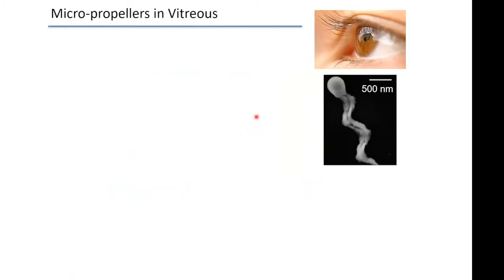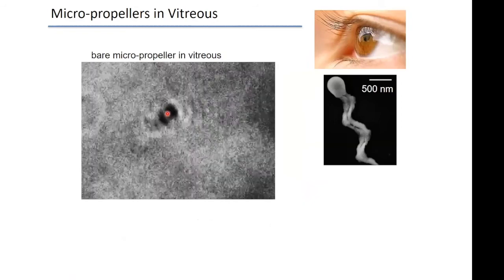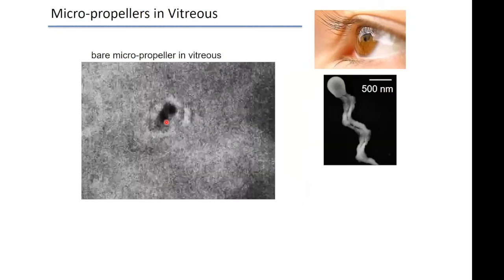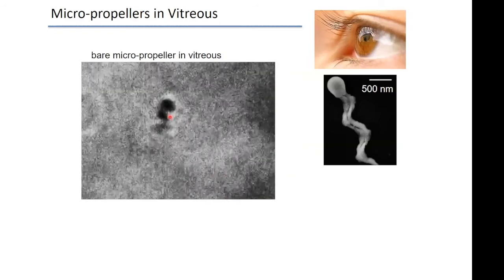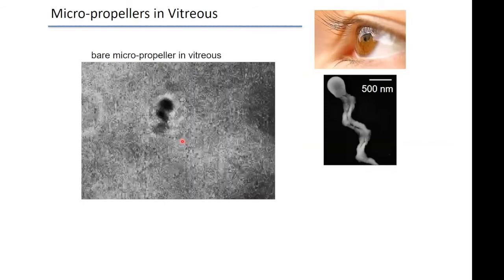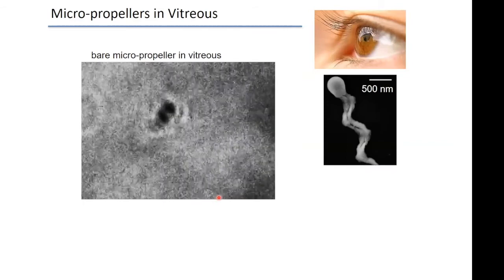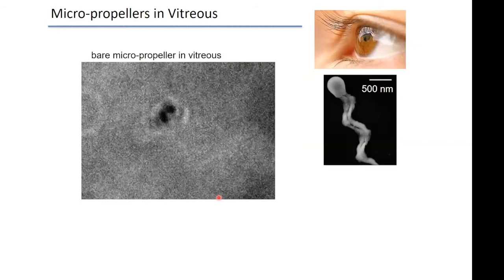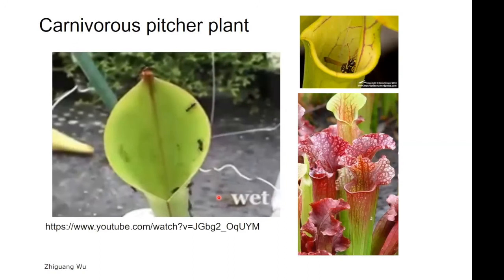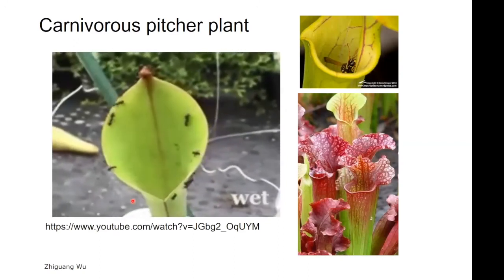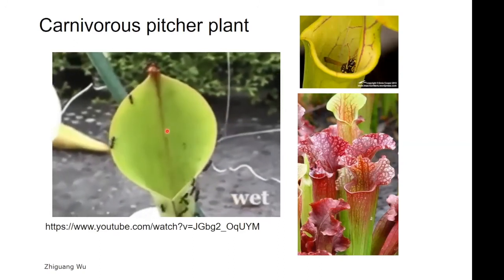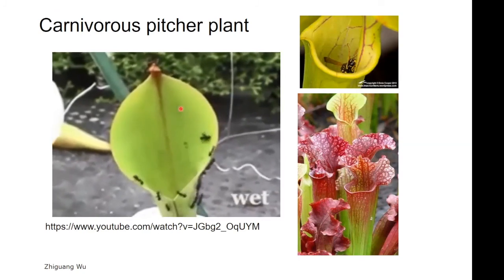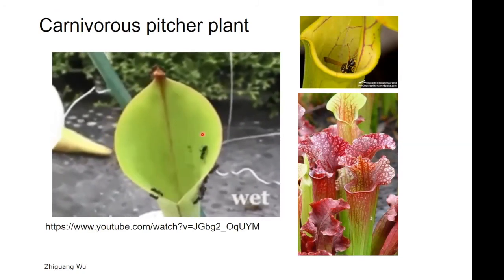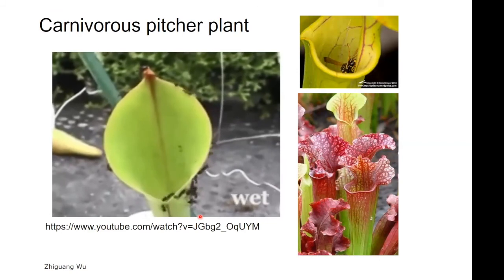And indeed, if we take our structure, and here is one, and we put it very deep into the vitreous, again, it has the size, it should move, but we have a problem again, it gets stuck. So in this particular case, the answer seems to be that we're dealing with this rather difficult environment where adhesion is a major problem. And so Zhiguang Wu took inspiration from nature. In this particular case, they're ants, and there are pitcher plants that have a very, very slippery coating, which causes them to fall in, and so the plant can eat them.